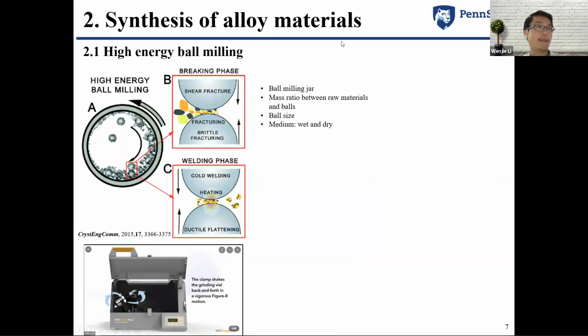of the alloy materials that we use for thermoelectrics, which can also be applied to high entropy alloys. The first and most widely used method for alloy material synthesis and preparation is high energy ball milling. This is a schematic diagram showing how it works. This is not the traditional planetary ball milling, where the ball and the jar only rotate one-dimensionally. High energy ball milling can provide multiple motions with the ball milling jar and make much more contact and generate more heat between the balls and the materials.